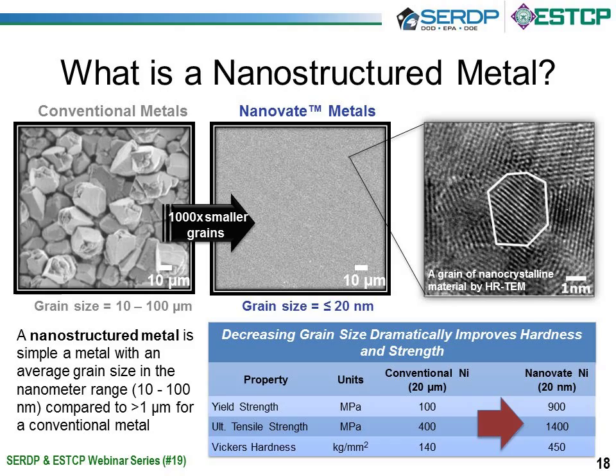And one of the biggest changes is related to the strength and the hardness of the material. As an example, with nickel, by decreasing the grain size from 20 microns to 20 nanometers, you get an increase in yield strength from 100 MPa to 900 MPa. So you see very high increases in strength. As well, you see large increases in hardness, in this case from 140 Vickers to about 450 Vickers.